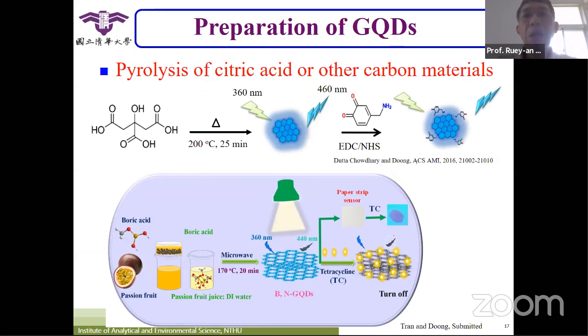How to prepare the graphene quantum dots? That's quite simple. You can try the top-down method. That means when you have your graphene family, reduced graphene oxide or others, you can use physical methods to grind and chop them into quantum dots. That's the physical method from top down. And from the bottom up, you can use chemicals. For me, I prefer the chemical method, because we can fabricate quite nice and uniform particle sizes.